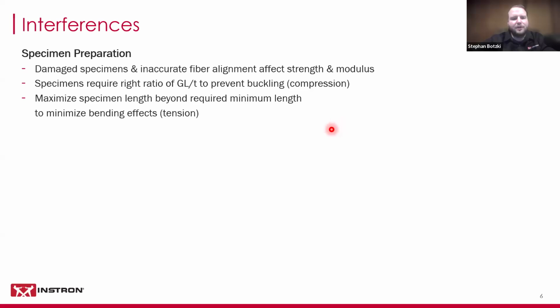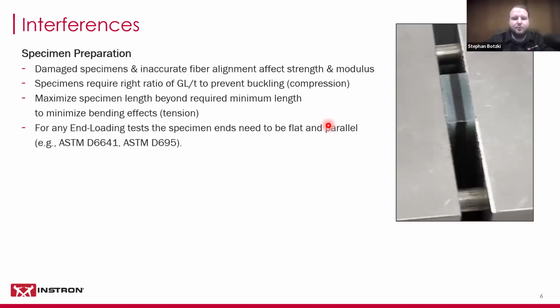On the other end, if you're doing tension tests, you should consider maximizing the length of your specimens beyond the minimum length requirements in the standards. There's typically, from what I've seen, not a maximum length. There's typically a minimum length. And now if you think about it, if you maximize that, any kind of bending errors that could be introduced from the grips, for example, would be minimized. The longer your specimen is, the less of an effect that certain amount of error will have, right? So if you just increase the length, that can help you with that.